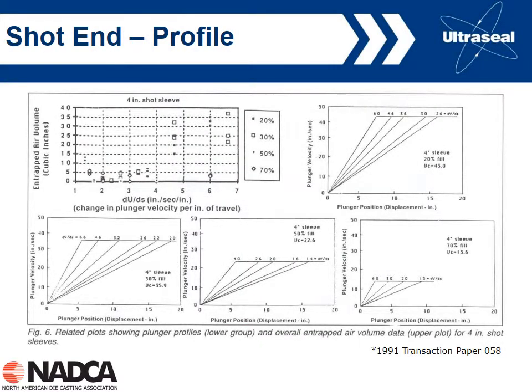And then here's some additional information about accelerating slow shot velocities. This is actually work performed prior to Marilyn Thome. This is from the 1991 transactions. Again, the paper numbers defined here. And again, it looked at accelerating slow shot profiles, accelerating at a constant rate. And so what we have is 4 graphs here, where each of the graphs is showing the plunger velocity on the y-axis, plunger position on the x-axis. It's all for 4-inch diameter sleeves, but it's for different fill ratios. So 20% fill, 30% fill, 50% fill, and 70% fill. And so it's looking at different acceleration rates under these conditions.